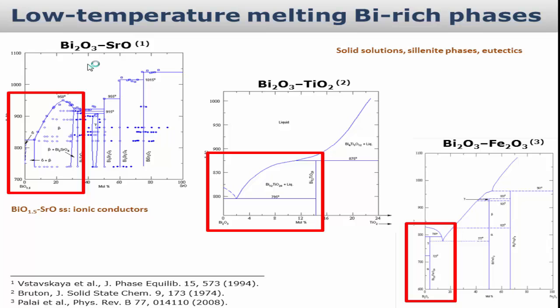You usually have these sillenite phases, so iron and also titanium will form the sillenite phase with bismuth, this bismuth-rich phase. And very often, like in the case of iron, this phase will decompose to melt into bismuth oxide at a temperature even lower than the melting temperature of bismuth oxide. So this temperature can be really below 800 degrees Celsius, where you typically calcine your samples. And you have these various eutectics with very low melting temperatures.